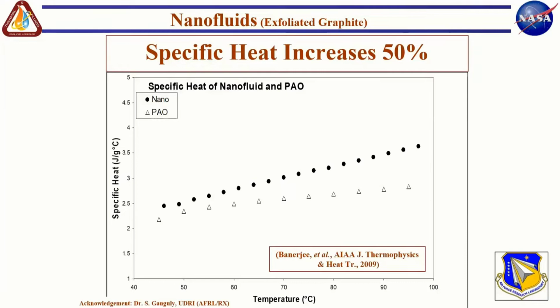And so the misunderstanding in the literature at that point was, people would measure the thermal conductivity of the nanofluid, they would measure the convective heat flux increase in the nanofluid, and they would assume the mixture rule for the heat capacity of nanofluids without measuring it. But one of the big advantages of being at Air Force Research Lab was we had ready access to a heat capacity measurement platform with a technician. So we didn't even have to learn how to use it. The technician did the measurement for us.